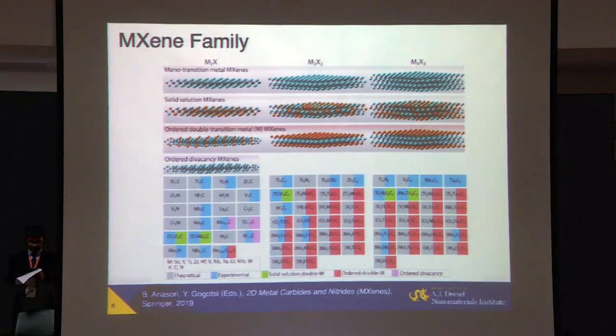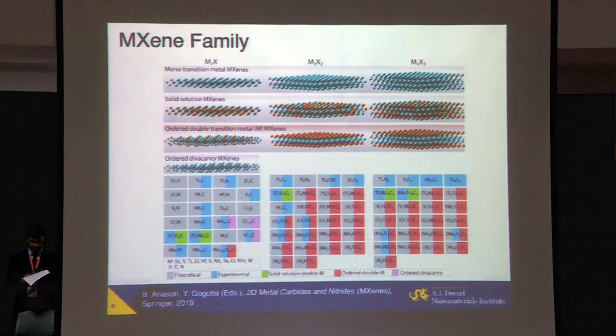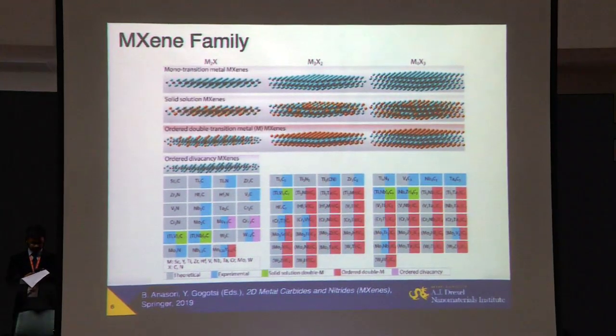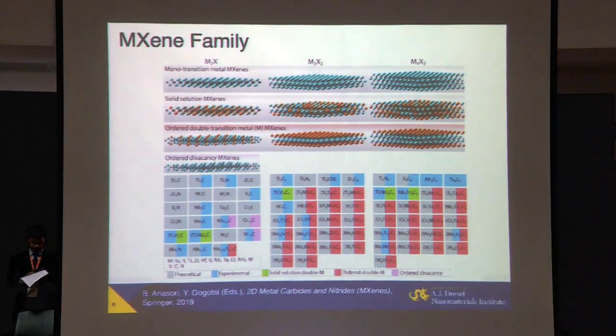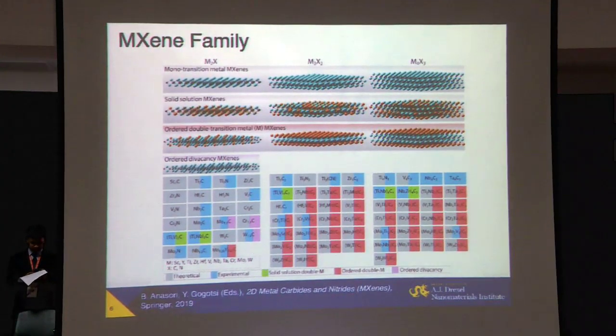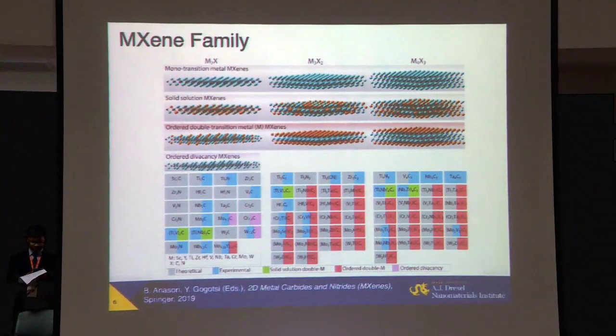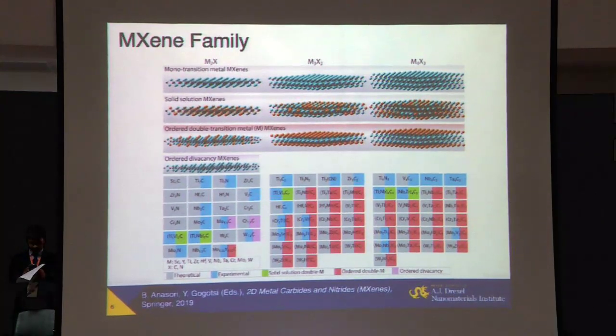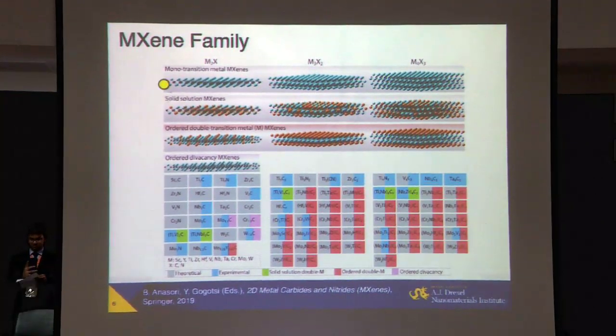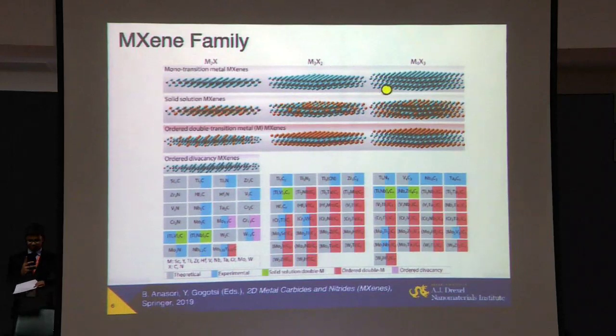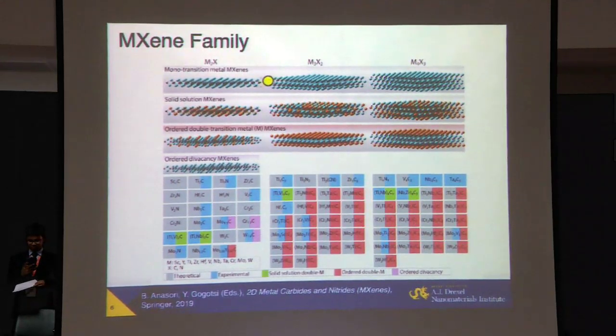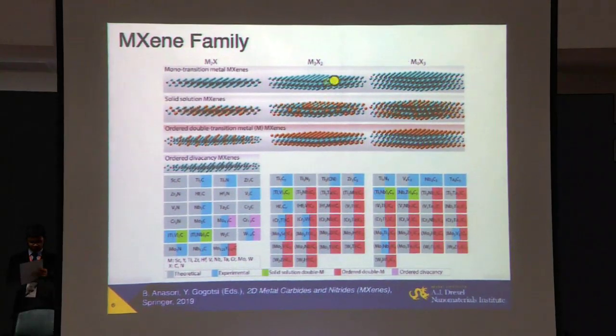So what do we have nowadays? We actually have a family with already at least 30 stoichiometric two-dimensional structures produced experimentally in the lab, at least 100 possible. So those are these mono-transition-metal MXenes, as I mentioned, M2X, M3X2, M4X3.